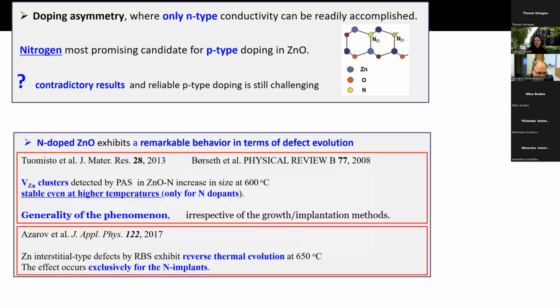Furthermore, nitrogen-doped zinc oxide exhibits a remarkably different behavior in terms of defect evolution. It has been previously reported that zinc vacancy clusters are extremely stable even at higher temperatures, and this happens only for the case of nitrogen dopants, and also they showed the generality of the phenomenon, meaning that it is irrespective of the growth and implantation methods. And also, a reverse thermal evolution of defects has been reported, meaning that there is a dramatic increase in defect concentration after annealing, and this happens again exclusively for the case of nitrogen implants.